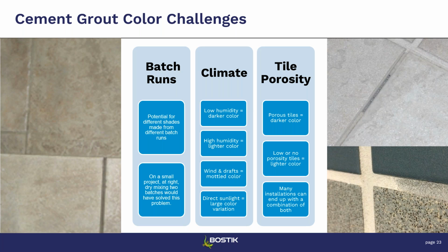You also have the porosity of the tile that can affect the grout color. So the more porous the tile, the darker the color. So again, the opposite, kind of like you saw in the climate, the less porous it is, the lighter the color. Many installations can end up with a combination of both high porous and low porous. So you want to keep that in mind as you go through and make sure you are using the right amount of water in order to help mitigate that. With these challenges, water tends to be some of the main reasons on why we do run into some of those.